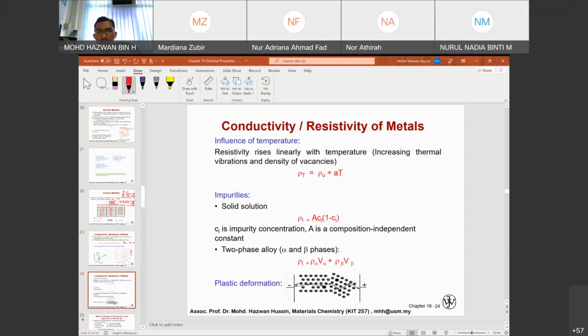Influence of temperature: resistivity rises linearly with temperature, due to the increasing thermal vibration and density of vacancies. Impurities: for a solid solution, resistivity rho equals A multiplied by C multiplied by 1 minus C, where C is the impurity concentration and A is the composition-independent constant. And for a two-phase alloy, if it does not exist in an isomorphous system, the resistivity equals the resistivity of alpha, rho alpha, multiplied by volume alpha, plus the resistivity of beta, rho beta, multiplied by volume beta.